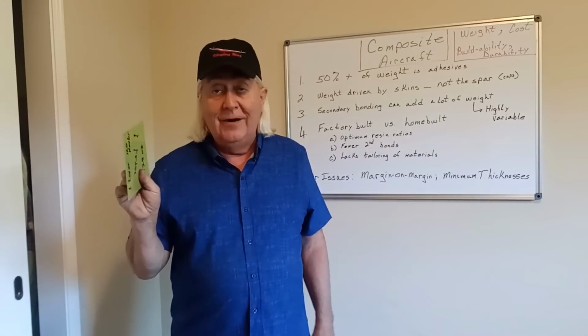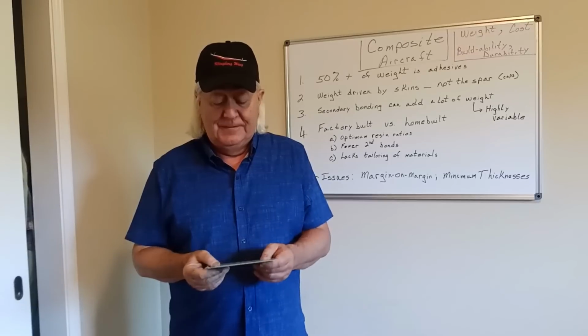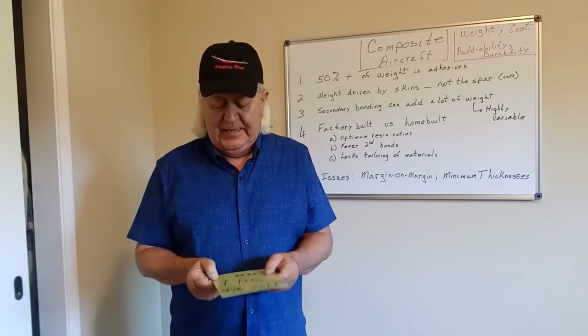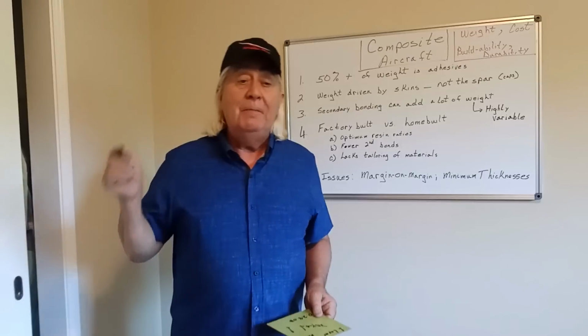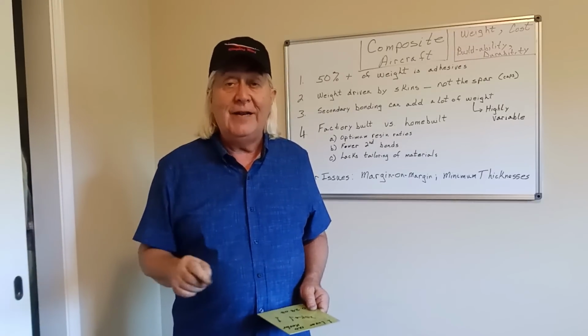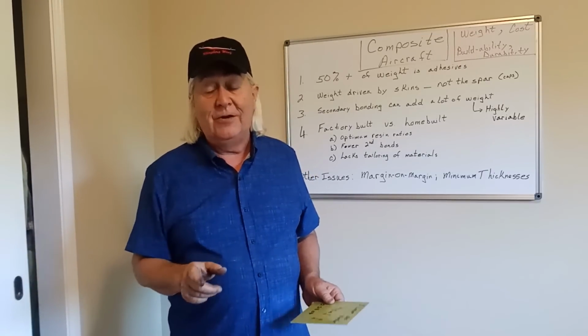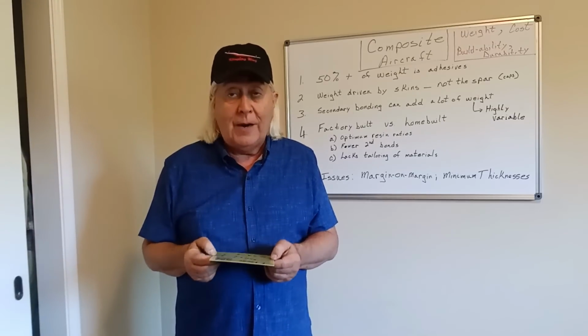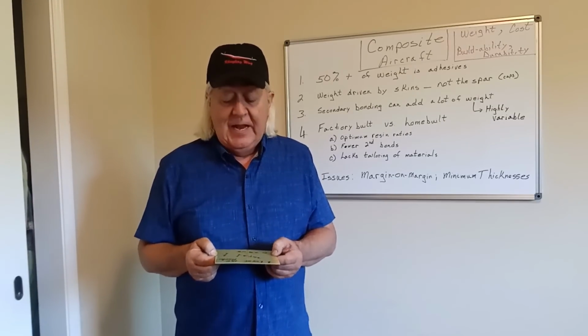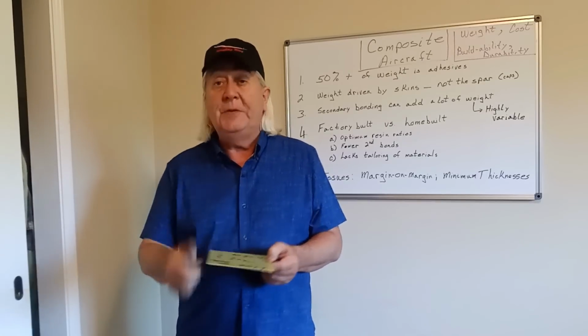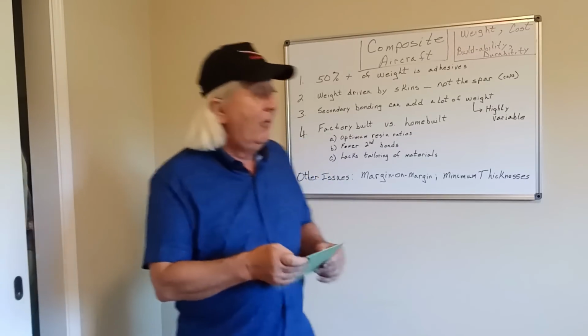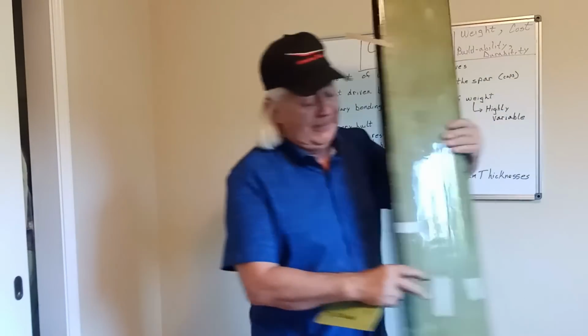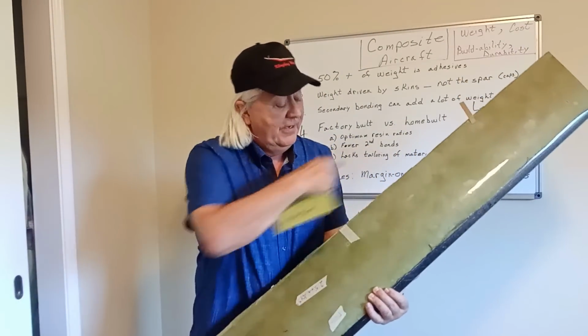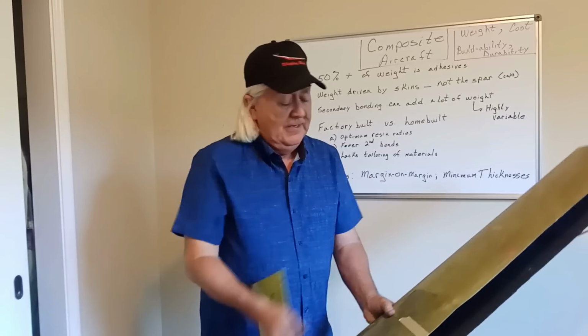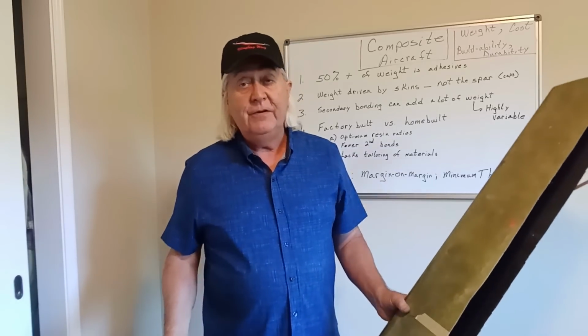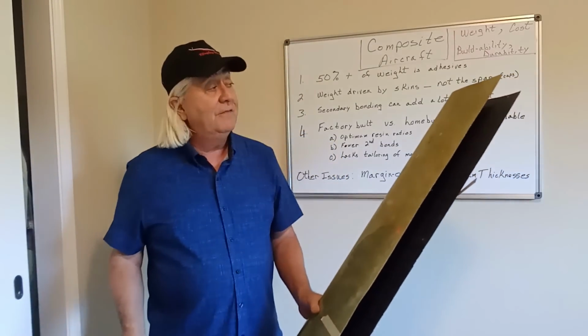So we're back to one layer of 120 Kevlar, and it has about the same dent resistance as the fiberglass, but the darn wing is transported in a bag. We haven't had really any problems at all with dents in the outer wing panels. So one layer of Kevlar is probably going to be good enough, and it'll be half the weight of the fiberglass, which would be super, because there's a lot of area in this tube here, this D-tube area. We got all of this area and all of this area, and it's going to save 3 or 4 ounces, if not more, 5, 6.